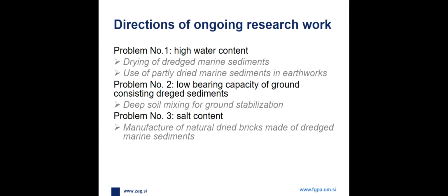The first two points are partly solved, while the other two are still in progress. The first problem is that this sediment, as explained previously in at least two presentations, is very wet, with too much water, and the traditional approach has been to pump up this material and deposit it in some lagoons, and it took a lot of time. So we try to do something with this. Then we have ideas to use these sediments in earthworks. Then those places where the sediments were deposited in the past are very difficult to use for construction. So very soft ground, and discussion on how to stabilize this ground. And the third thing, can we manufacture something out of those sediments?